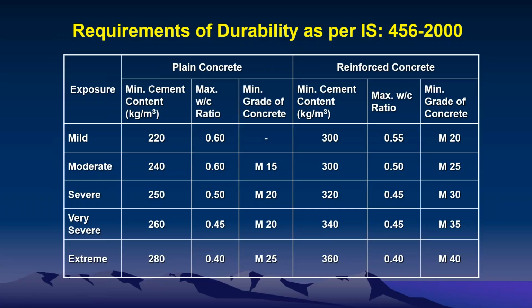Now I am reproducing Table 5 of IS 456. So again, the same exposures: mild, moderate, severe, very severe, and extreme. This is for plain concrete. I'm not bothered with plain concrete; I'm more bothered about reinforced concrete. So certain prescriptive parameters have been given: minimum cement content, maximum water cement ratio, minimum grade of concrete. Now I want to address this in this lecture.